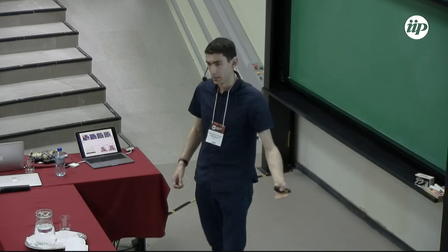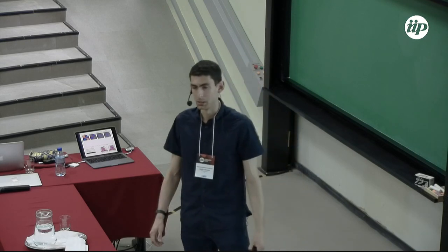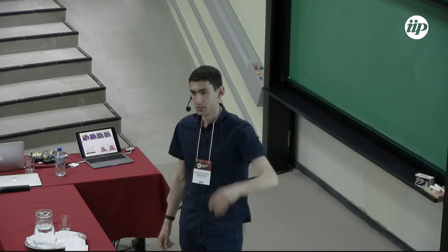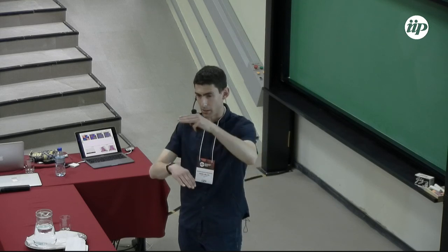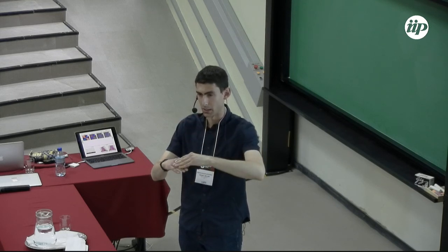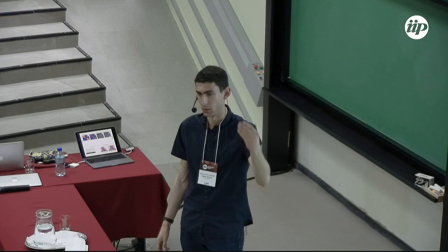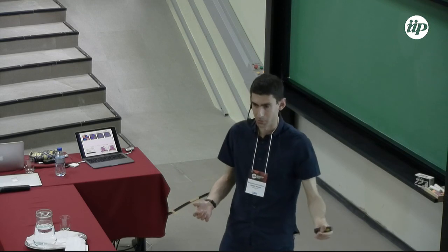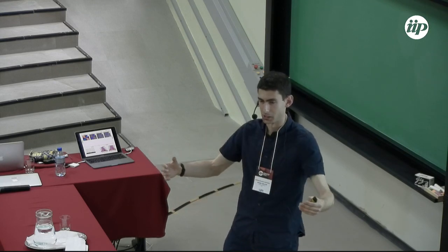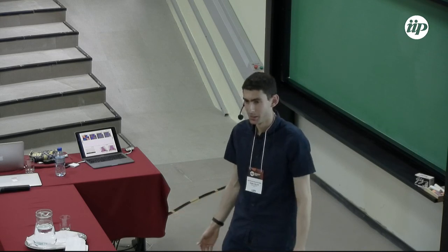Right, so assuming you're at equilibrium, it's an energy minimization where if you had infinite thickness, it would just be set by, yes, they do. So it's limited by the thickness of the sample, but it's not directly proportional because you have this other length scale of the elasticity over the anchoring strength. Those interact to give you the energy landscape for one focal conic domain, and then you want to minimize over the size in a packing, so the energy per unit area.